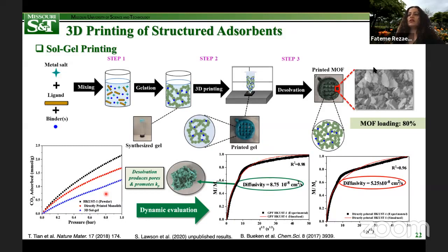And we believe that this low capacity was obtained because we didn't get 100% conversion of precursors to the final MOF. The fractional uptake measurements and the corresponding diffusivity values estimated from these profiles indicated that desolvation, or solvent removal, produces large mesopores that promote effective diffusivity to the hierarchical pore network. In addition, the gelated monolith gave better mass transfer than the directly printed monolith for the same MOF because it had an open mesopore structure, which enhanced the rate of mass transfer.